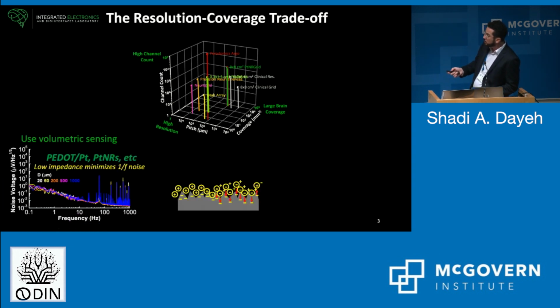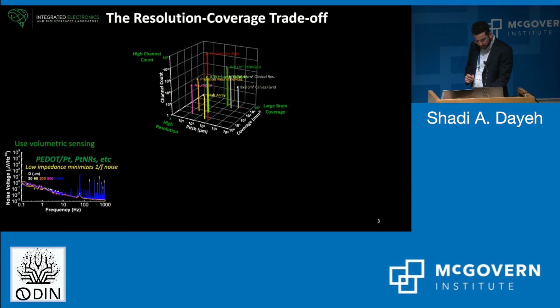Now, if we go to volumetric sensing materials like polymers, or if we go to roughened surfaces where we have both sharp tips and sharp corners that facilitate the electrochemical interactions, and also a large surface area, the number of adsorption sites increases, random processes have less of an effect, and then the 1/f noise is plateaued at the amplifier noise for all of the microelectrode diameters.